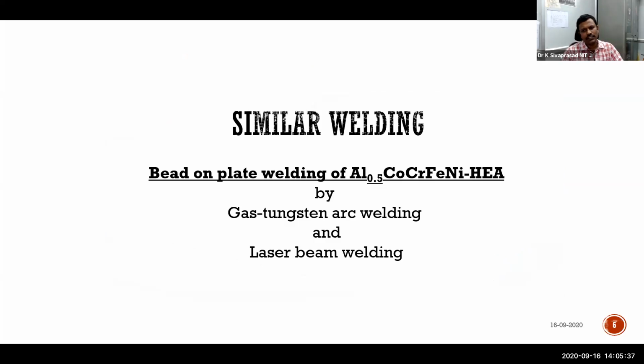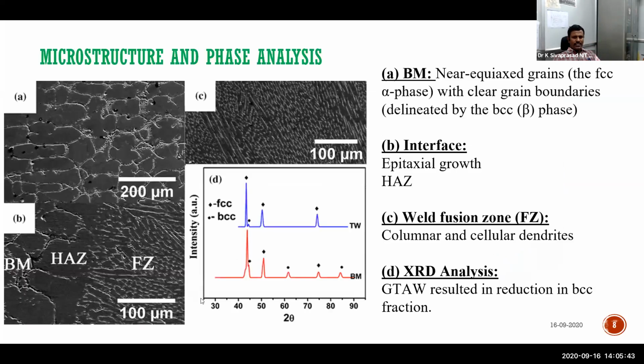Then first we have started with similar welding with Al 0.5. Gas tungsten arc welding and laser beam welding were performed. Gas tungsten arc welding has clearly shown a typical arc welding geometry, fusion welding. Any FCC structure fusion zone will be like this. If you take austenitic stainless steel, nickel based copper alloy, or even this high entropy alloy, all appear to have a similar cellular kind of dendritic structure. Partly cellular, partly dendritic kind of structure was observed.